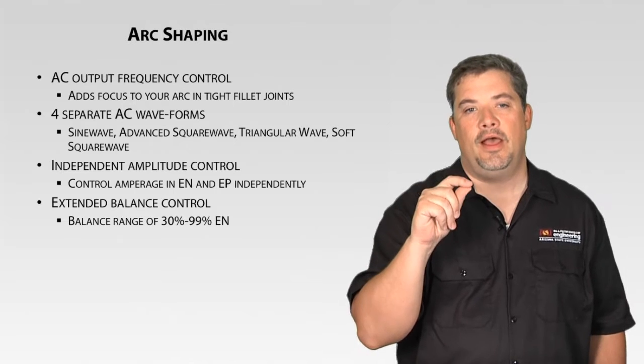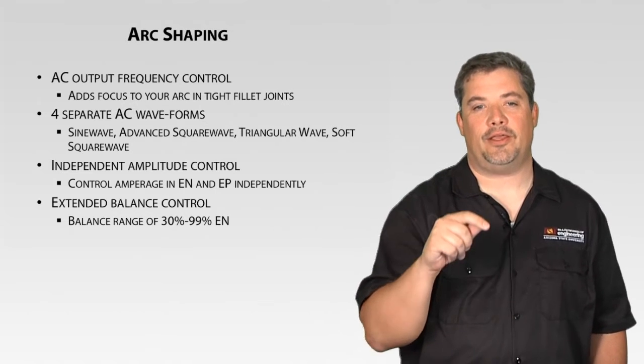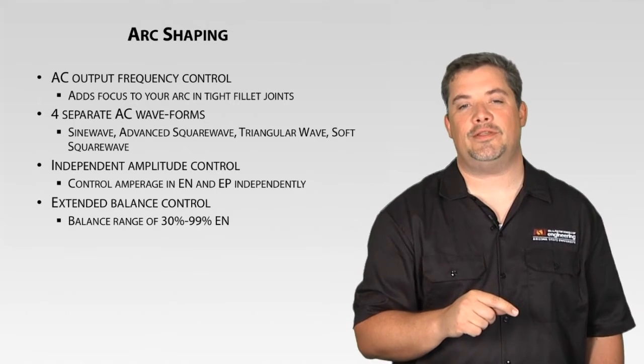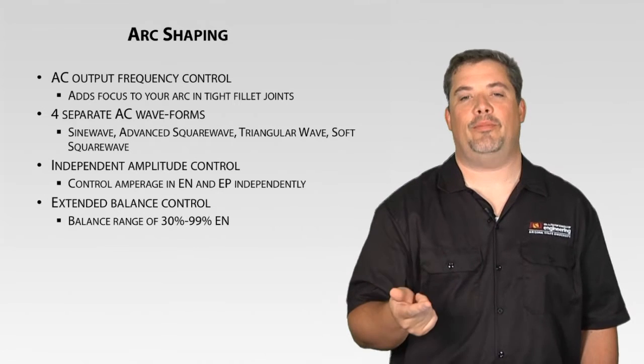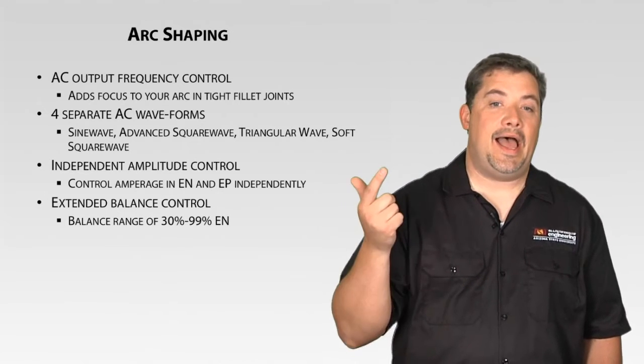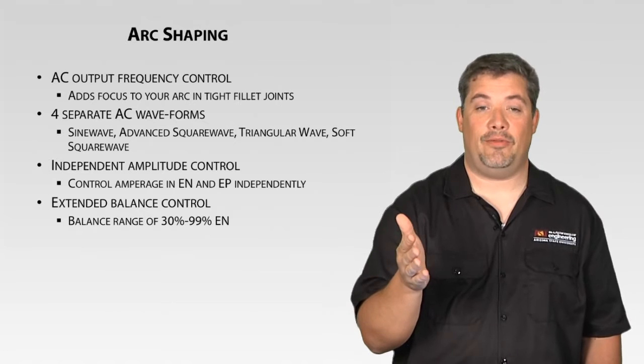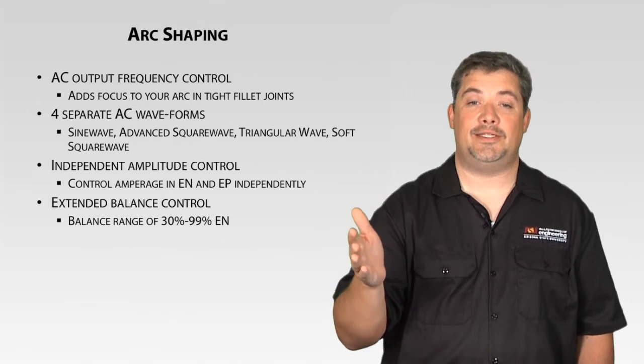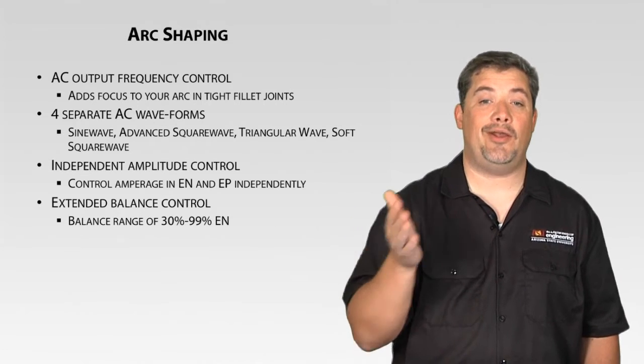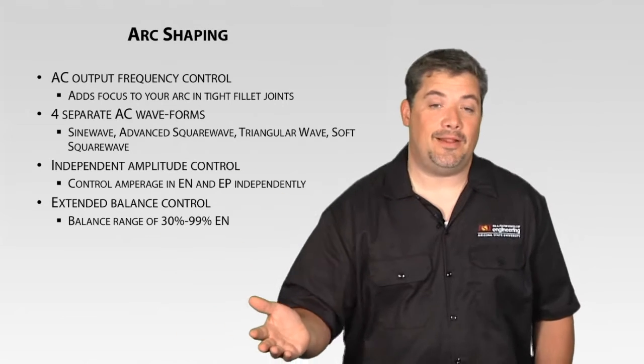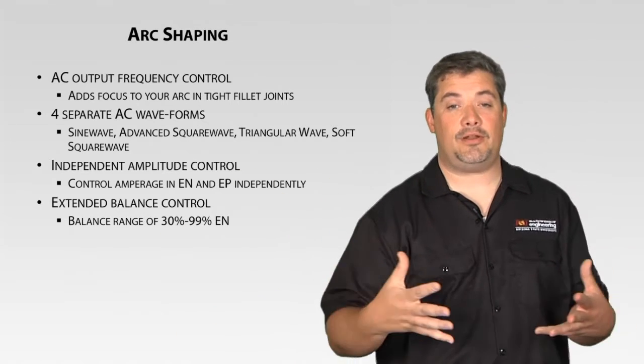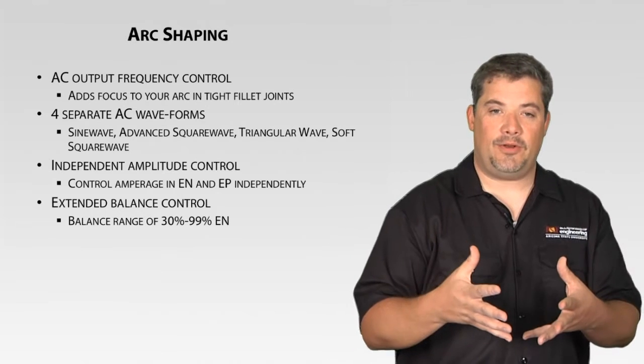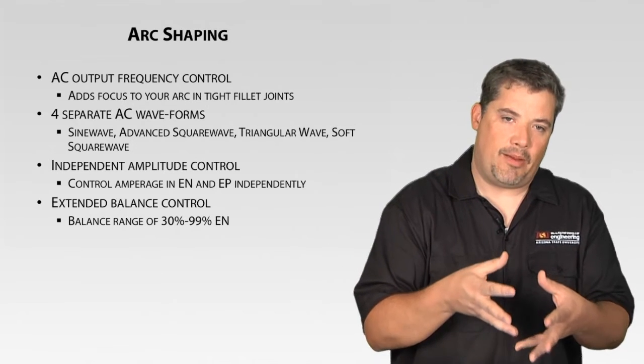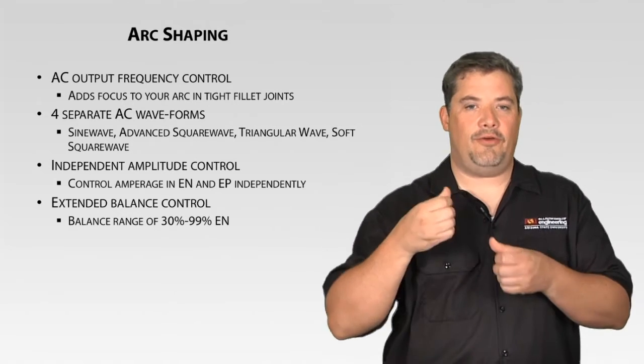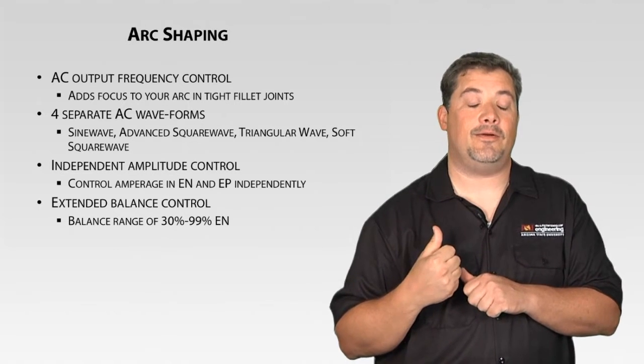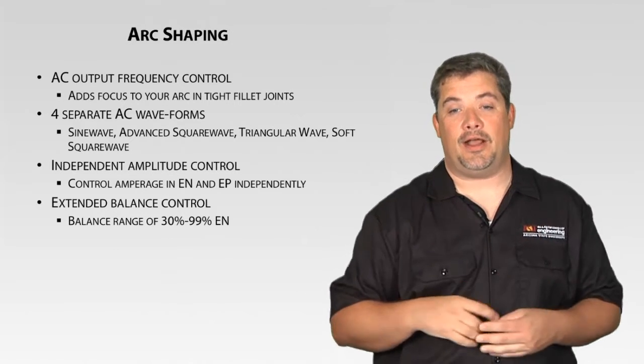efficiently. I have independent amperage control, so I can control how much amperage I'm on the positive half of the cycle and have it be a different level of amperage on the negative half of the cycle. I can take that balance control we just talked about that went from 45 to 68% electrode negative. Well, now I can go from 30 to 99% electrode negative. So now I can really start to take advantage of that electrode negative half of the cycle that's putting heat in my part, but just use enough of that electrode positive half of that cycle to let me etch that oxide layer out of the way.